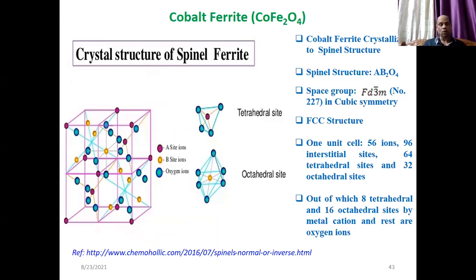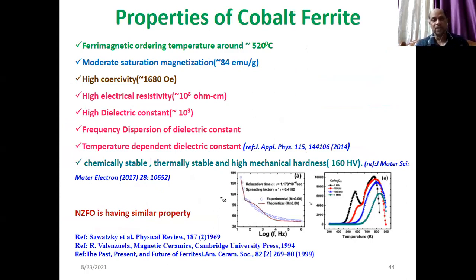And the other one is cobalt ferrite. It is a very good hard ferrimagnetic material, and it becomes soft very easily by modifying its chemical constituents or by creating defects in the material. It has a spinel structure. Okay, so it has different properties, and if you look into why these materials are so prominent, it is because all their properties are above room temperature. At room temperature, they show good properties. That's why people are happy to pick up these materials to be utilized for industry.